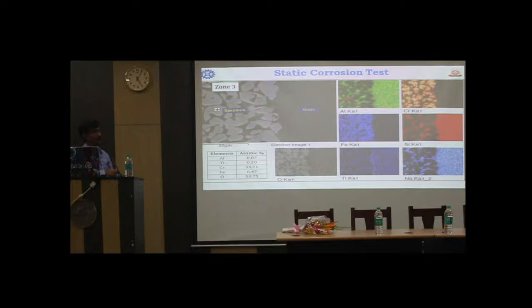You see that the chromium grain is there. Suppose this grain, you see this is the grain. So the chromium concentration is more, but in the same grain, aluminum concentration is almost nil. And see about the iron oxide. When the chromium is there, at that time, if we can magnify, iron oxide is also there. So that means what happens? Initially, this is alumina chrome. Now this aluminum is migrating from the aluminum chrome solid solution, and the iron oxide has a similar type of structure, and then the iron enters into the crystal structure.